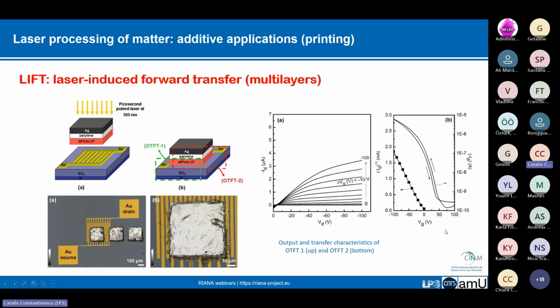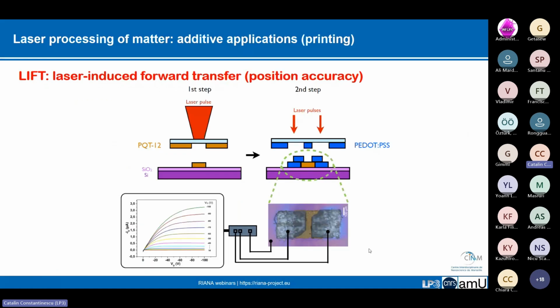We can also understand how this precision is at the heart of LIFT by explaining how we printed fully organic devices this time. In this case, we had an electrode of PEDOT:PSS and a pixel of semiconducting material, PQT-12, a polyquaterthiophene. We printed in several steps, so it's a technique that allows multi-step device fabrication with excellent reproducibility because we printed several devices. This can be integrated, and therefore it's essential for organic electronics and microelectronics in particular.